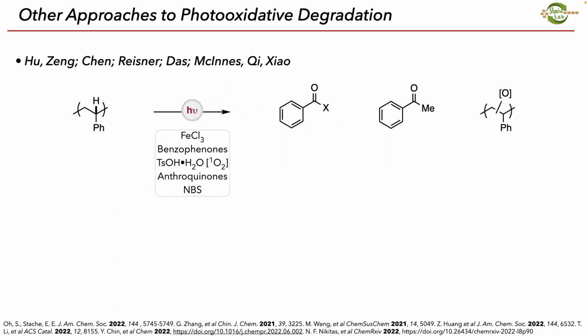And so when we published this work on polystyrene photooxidative degradation, a bunch of other people published papers at the same time. So this area has gotten very popular. A lot of people are looking into polymer recycling. And so a number of different strategies were used, using iron trichloride, using benzophenones, singlet oxygen, anthraquinones, NBS. And in all these cases, the bond dissociation energies are greater than 100 kcals per mole.